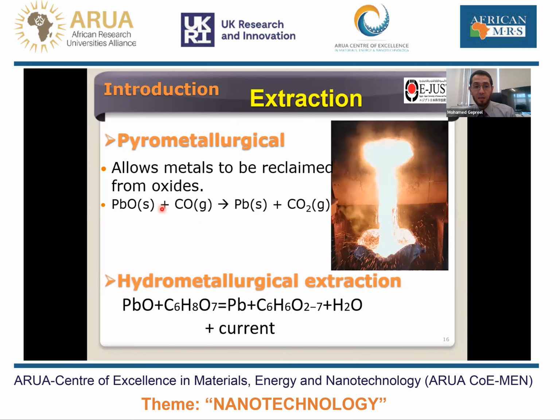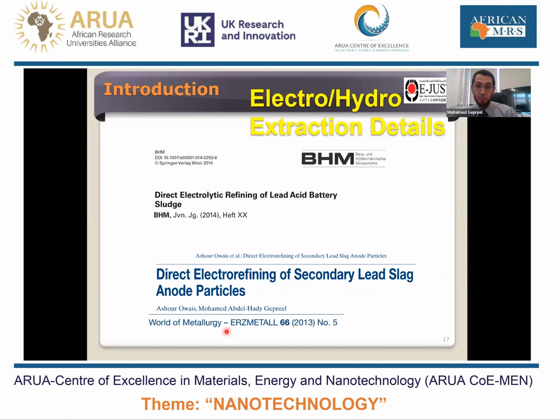reduction by some gases like CO to get liquid lead and then solidify it, or hydrometallurgy, where we use an electrolyte to reduce the lead oxides to get lead sediments and so on. And sometimes we also consider electrometallurgy, which is hydroelectrometallurgy, where we use a power supply and current for accelerating and controlling the production and reduction process.